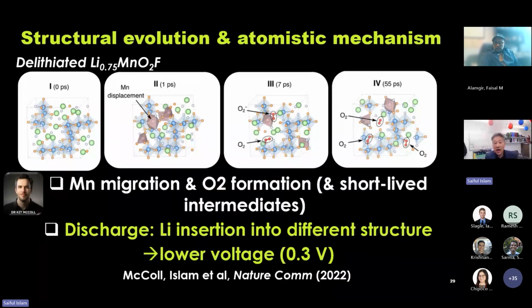And then on discharge, when we put lithium back in, we're putting lithium into a very different structure because of the manganese migration, and that leads to a lower voltage and hence a voltage hysteresis on first cycle.